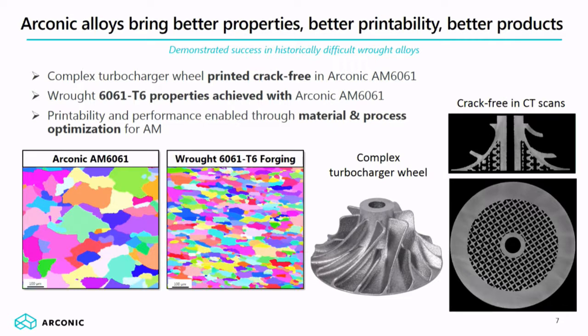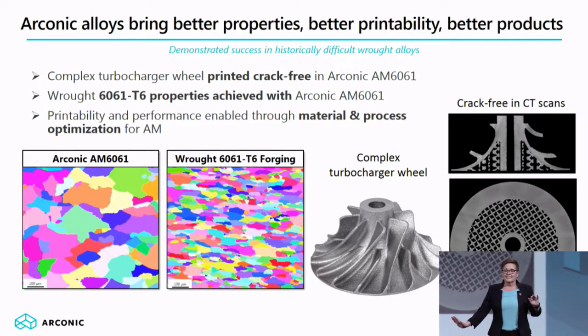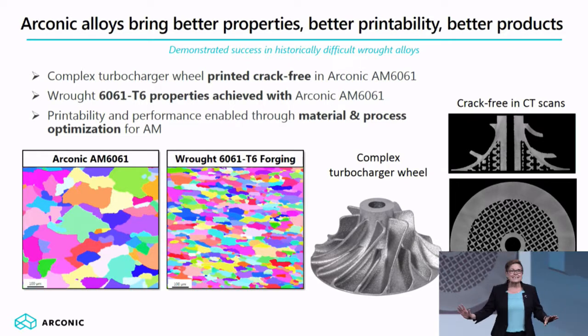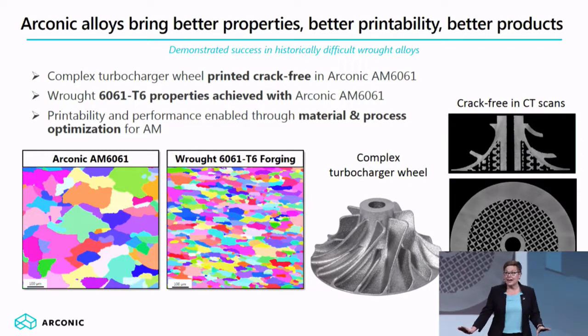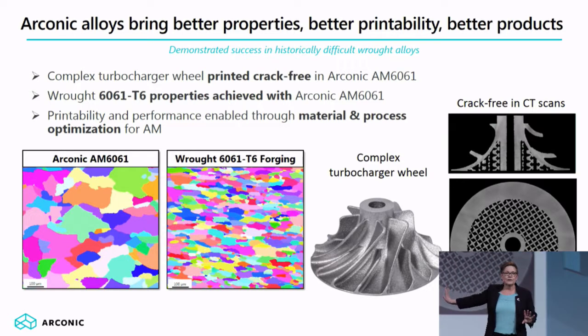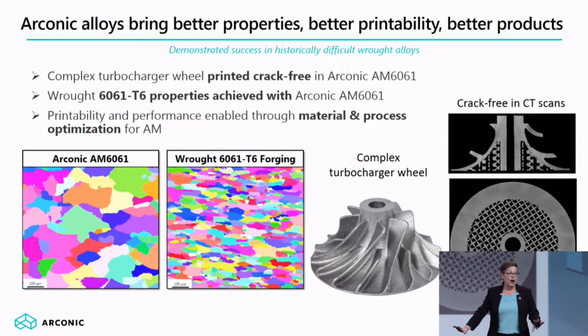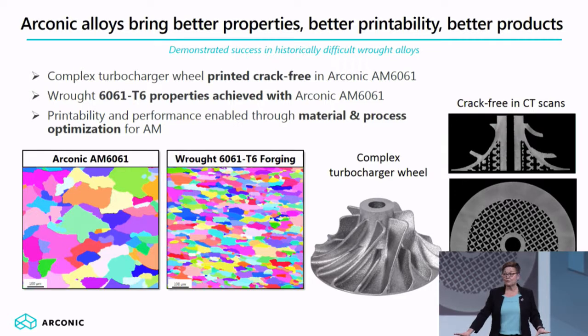Furthermore, we've demonstrated that we can take the ideas we used to develop this AM6061 and apply that to the 2000 and 7000 series alloys, also making them crack-free and printable. So we're doing this by optimizing our materials, optimizing the additive manufacturing processing in order to create the desired microstructure. On the slide behind me, you can see that we've created a comparable microstructure in our AM6061 to that which we see in our 6061 T6 forgings.